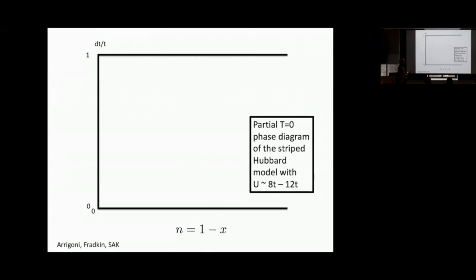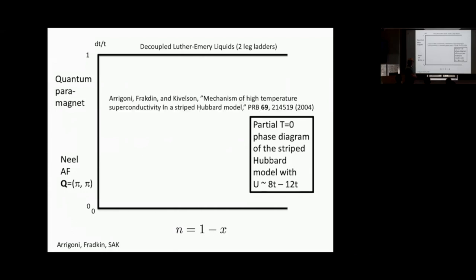Right, so at small dt, it's the same as dt equals 0. We're going to have a Néel antiferromagnet at 0 doping. But at dt equals 1, we have a system that consists of decoupled 2-leg ladders. And so the individual 2-leg ladders, when they're doped, are known from very extensive DMRG work to form Luther-Emery liquids. And on the undoped system, the striped antiferromagnet has a quantum paramagnetic phase and a phase transition between these somewhere here.